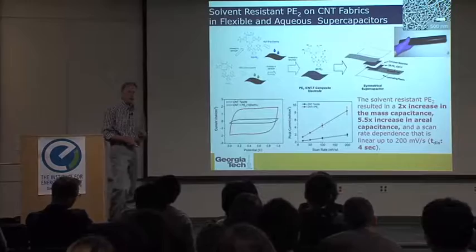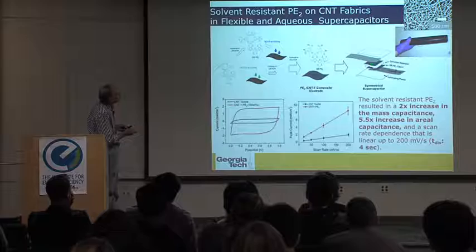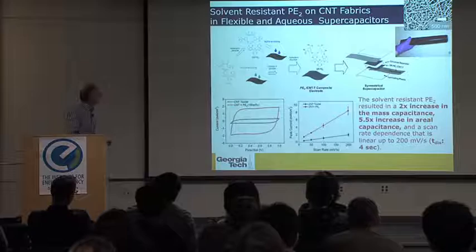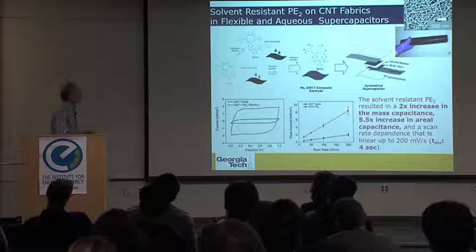And then we create one of these capacitors using graphite foil as a contact. The solvent resistant PE2, and that's a carbon nanotube textile, are the two blue things here. And then we have a cellulose separator in the system. What you can see is we can pile on 150 weight percent of the polymer onto the carbon nanotube textile, and you can see the increase in the overall capacitance from the system. In this case, we took it out to 200 millivolts per second just to demonstrate it would